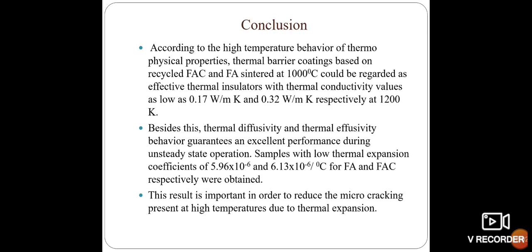For the conclusion, according to the high temperature behavior of thermophysical properties, thermal barrier coatings based on the recycled fly ash cenosphere and fly ash sintered at 1000 degrees centigrade could be regarded as effective thermal insulators, with thermal conductivity values as low as 0.17 watts per meter Kelvin and 0.32 watts per meter Kelvin respectively at 1200 Kelvin. Besides this, the thermal diffusivity and thermal effusivity behavior guarantees an excellent performance during unsteady state operations.